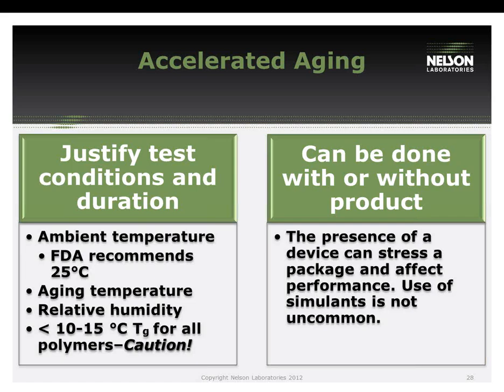The ambient temperature that FDA looks for is at 25 degrees. This is a value that's actually very warm. Most warehouses are a lot more controlled than this. And if time is an issue, this is the value that you would want to look at possibly. The lower the ambient temperature, the faster your samples will age. And if you have documented evidence that your warehouse or the facility that your products are going to be located at are less than 25 degrees, go ahead and use that.